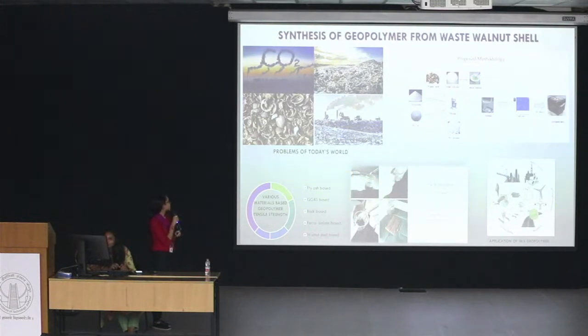My methodology is that I'm using fly ash, metakaolin, walnut shell, and solid activators, which are prepared 24 hours before the mixing process. Then the process is done and the geopolymer is formed. We found that the tensile strength of the walnut-based geopolymer is more than that of other geopolymers. Applications are construction materials, pavements, and fire resistance. It is also used in railways and many more things.